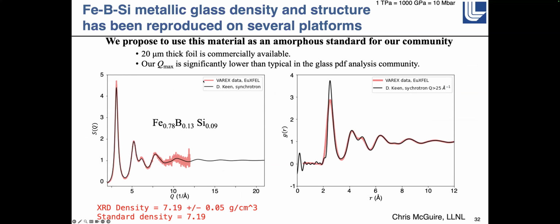As an approach to that, we looked at a metallic glass at the European XFEL. The data is the pink one here. D. Keen also measured it at the Diamond synchrotron in England, and he measured it out to, I think, 35 inverse angstroms. The black line is what he got. Our analysis gives the structure factor in very good agreement, and G of R is also in very good agreement. The broadening and weakening of the first sharp diffraction line is essentially because of the Q cutoff that we're forced to use.